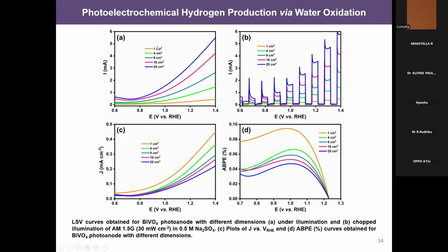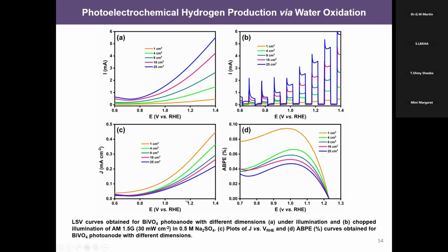So here, when we increase the area, the photocurrent got increased. But I just want to see whether this 1 centimeter square behaves like a 25 centimeter square. For that, I have converted into current density. So now the trend will be reversed. So here the efficiency also decreases as the area increases, due to the high charge recombination process and the charge transfer resistance.